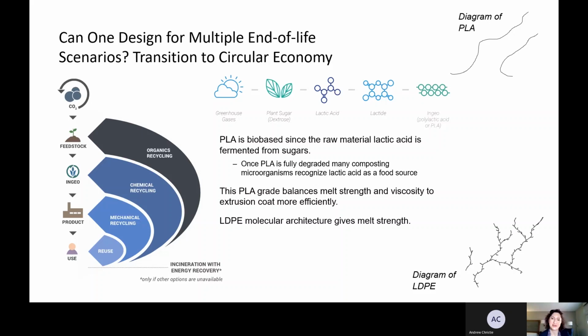And once PLA is fully disintegrated, many composting organisms recognize lactic acid as a food source. In fact, we all have lactic acid in our bodies. When we have a hard workout, we get sore muscles, and that soreness is from the lactic acid that our own body generates. So, PLA fits in many end of life scenarios. It can be reusable, it can be mechanical recycling, and it can be chemically recycled by bringing it back down to lactic acid. And in organics recycling or composting, the PLA breaks down with time and temperature to lactic acid, which is recognized by those microorganisms.